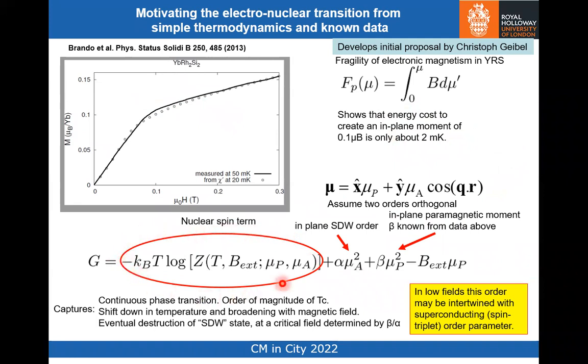So this is the energy of the nuclear spins, which are experiencing a hyperfine field. We're not considering anything to do with interactions between nuclear spins. They're just experiencing the hyperfine field due to the electronic magnetism. And the electronic magnetism has two origins. There's the in-plane moment that's induced by an applied magnetic field, and then there's the amplitude of this, in inverted commas, spin density wave order that's appearing spontaneously below 1.5 millikelvin. And we assume that those two moments are orthogonal to one another.